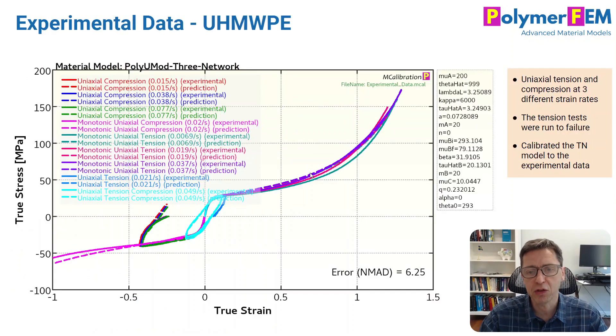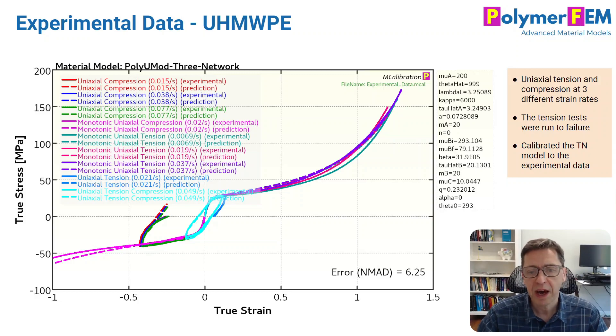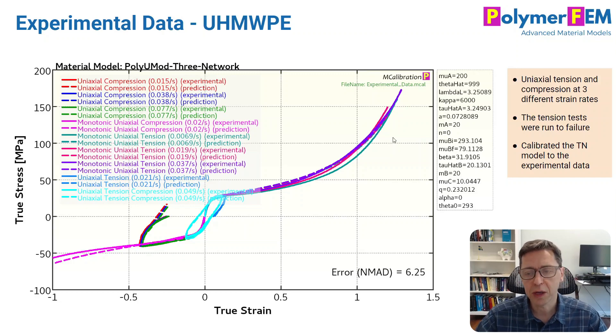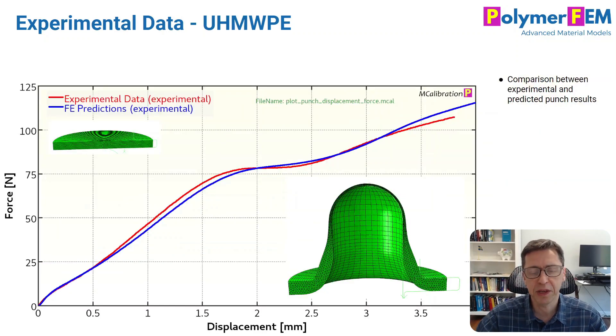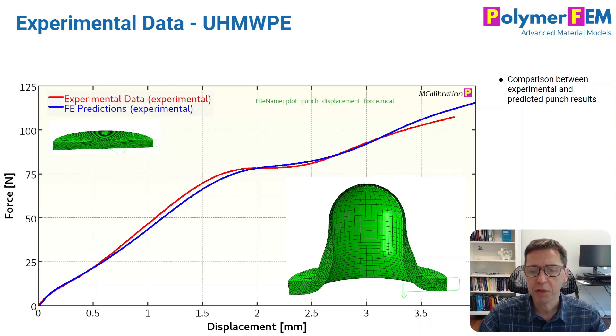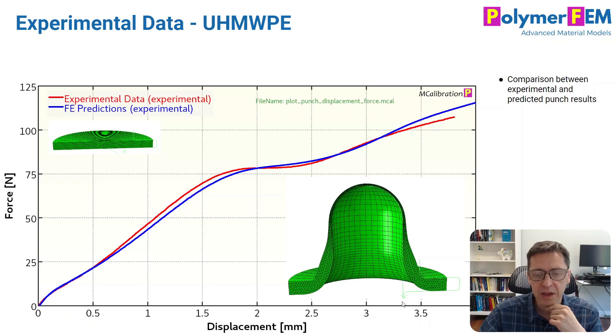I have an example to illustrate this. My example is based on ultra-high molecular weight polyethylene — polyethylene with very long molecules, used in orthopedic implants and many other things. I tested this material a number of years ago in monotonic tension, cyclic tension, and compression, so I have data for it all the way up to failure. I calibrated a material model to this data that can predict the response very well. Then I simulated an additional experiment: a punch test, where a disc of this polyethylene is punched with a spherical metal punch, as shown in this finite element simulation.